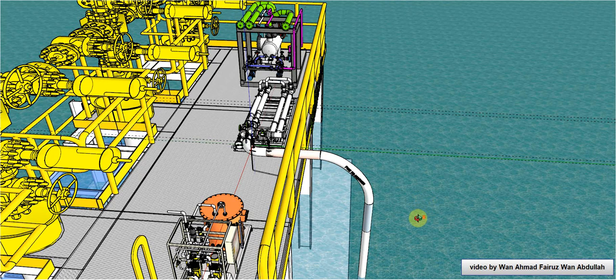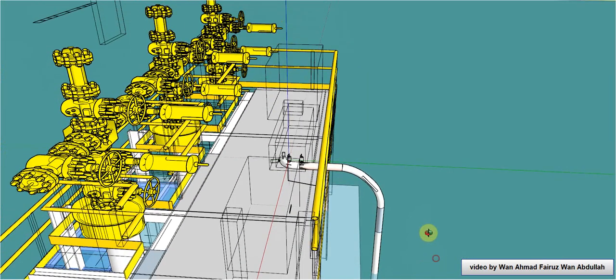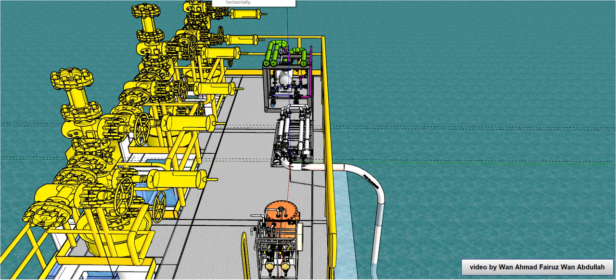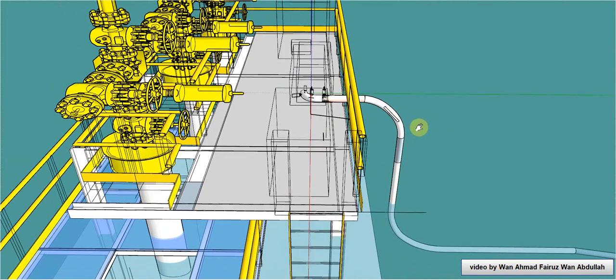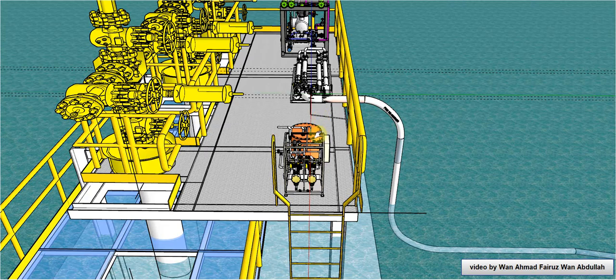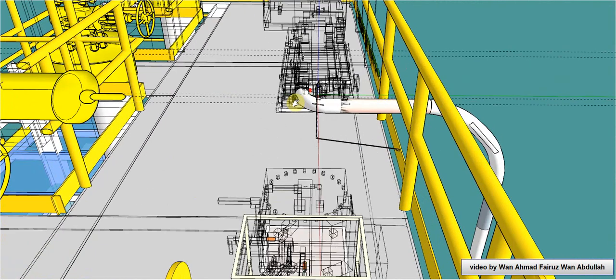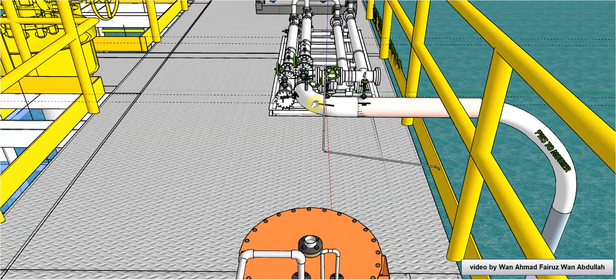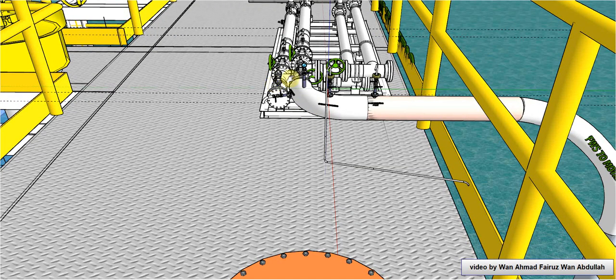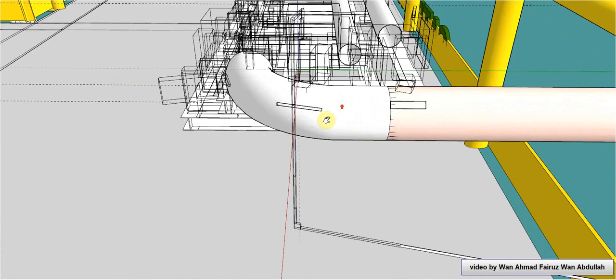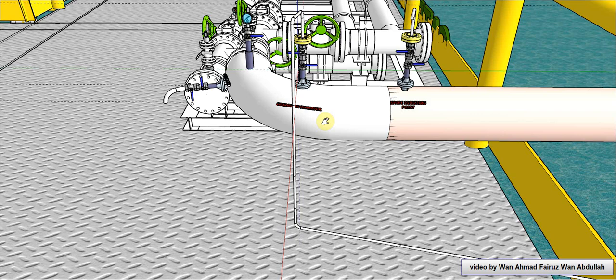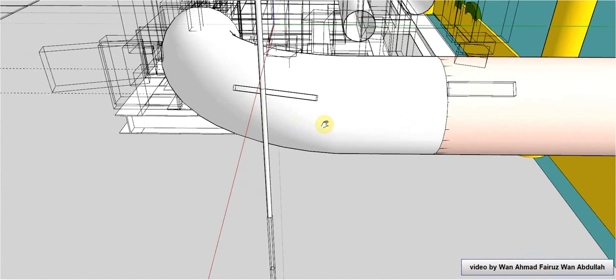To make sure of the integrity of the sampling, remember the precautions prior to taking the sample. We need to stop the particular chemical injection at the wellhead. For example, the chemical demulsifier needs to be stopped for 15 minutes and the corrosion inhibitor injection stopped for 2 hours. This is to ensure the samples are not contaminated with chemical and to prevent haywire data.